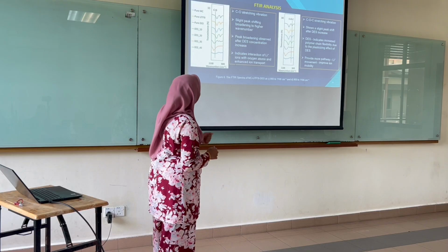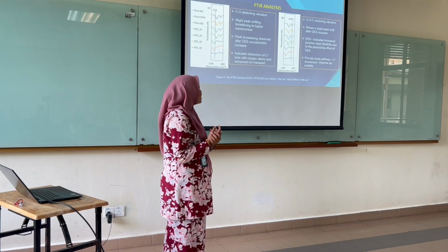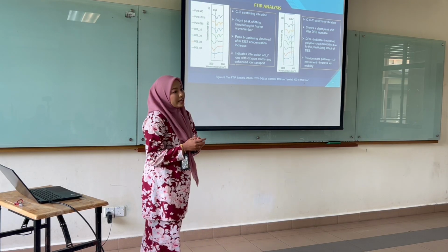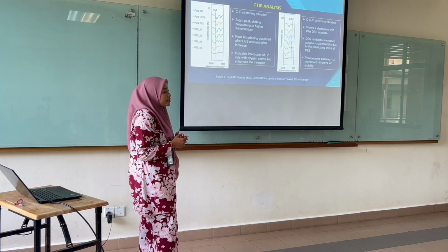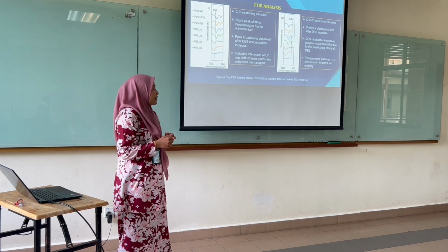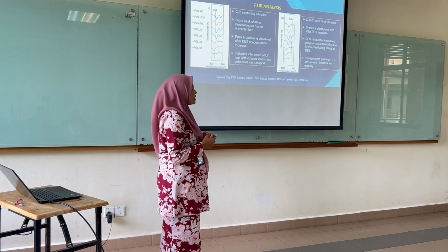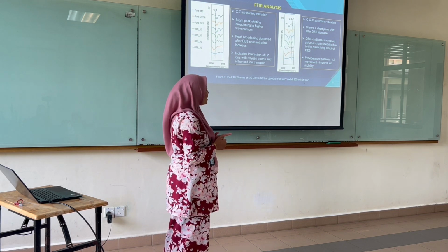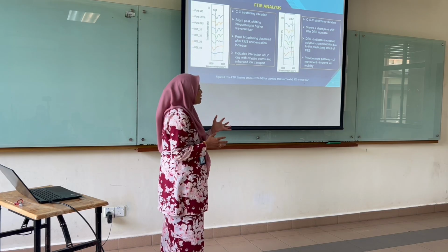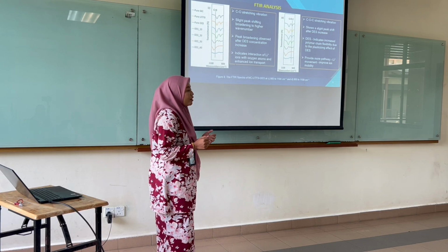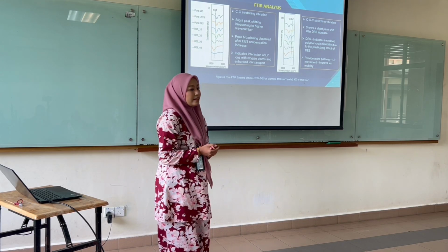Next, FTIR spectra for the CO region and COC region. The CO stretching vibration shows slight peak shifting and broadening to the higher wavenumber. The peak broadening observed after the DES concentration was increased indicates the interaction of lithium ion with oxygen atoms and enhances the ion transport. Next, the COC stretching vibration shows a slight peak shifting after DS was increased. This indicates increased polymer flexibility due to the plasticizing effect of DES, providing more pathways for lithium ion movement and improving ion mobility.